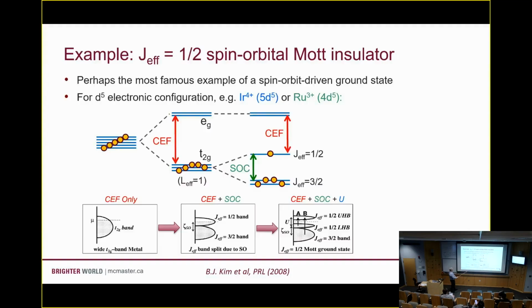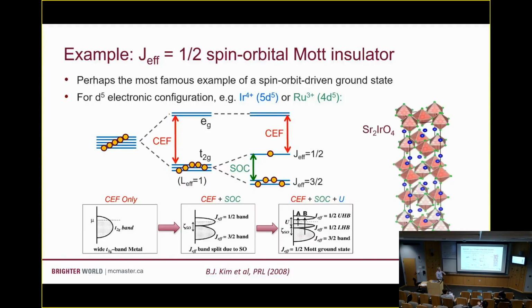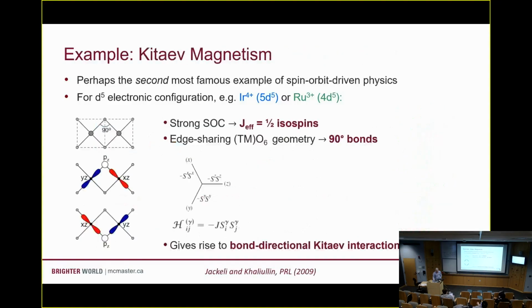But instead, you get the combined effects of the crystal electric field, and then the spin-orbit coupling can split your t2g levels into a lower J-effective 3/2 manifold and an upper J-effective 1/2 manifold, and then here you have a half-filled J-effective 1/2 band. Even a pretty weak U is enough to open up this insulating gap, which is exactly what's seen in materials like strontium iridium oxide. Okay, so this is the canonical example of a spin-orbit Mott insulator.